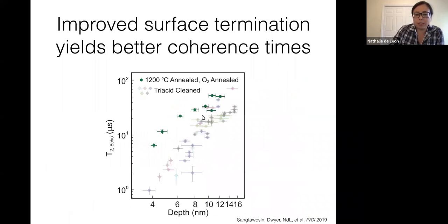What we were able to see immediately just from doing this very long sequence is that we're able to get NV centers with coherence times that are better by almost a factor of 10 for the same depths. So all of these points are what I showed you earlier, whereas these dark green points are our typical best NV centers from all of this processing.